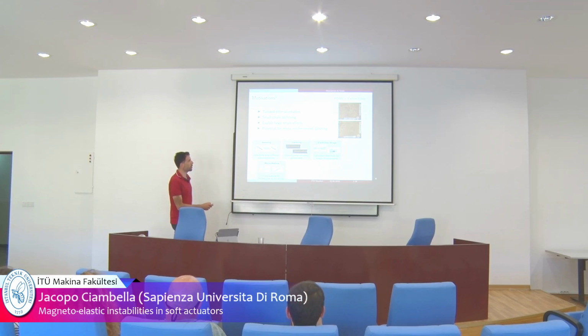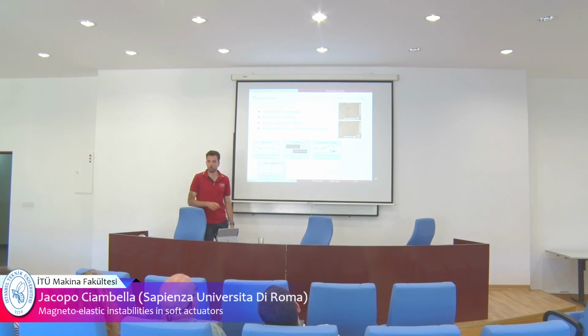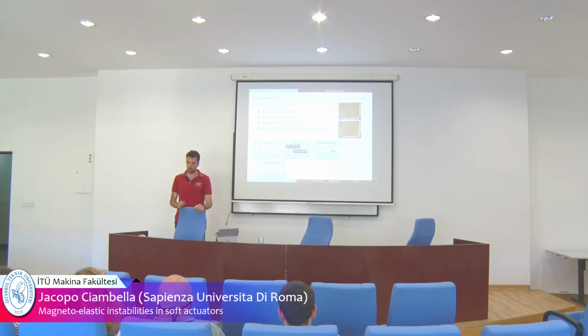The material we used in most of the presentation is PDMS, a silicone elastomer, very soft, reinforced with carbon fiber. Not exactly carbon fiber, but as I will show you, nickel-coated carbon fiber. Why the nickel coating? Because this improves the magnetic properties of the fiber. Consider that we are talking about Young moduli of the order of 10 megapascal, so a relatively soft material.